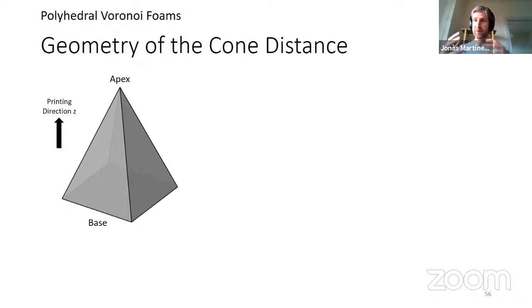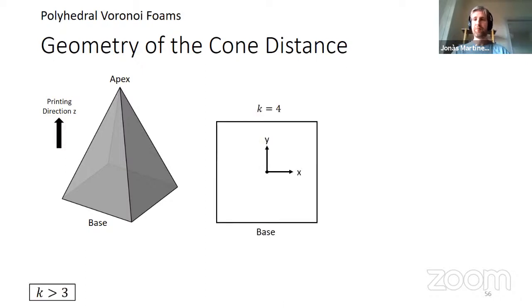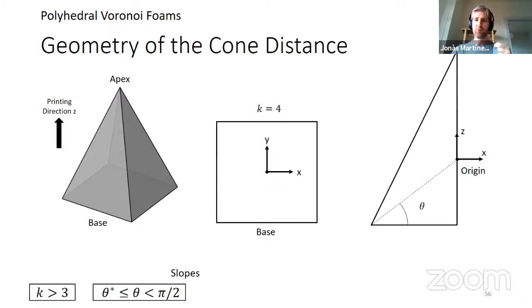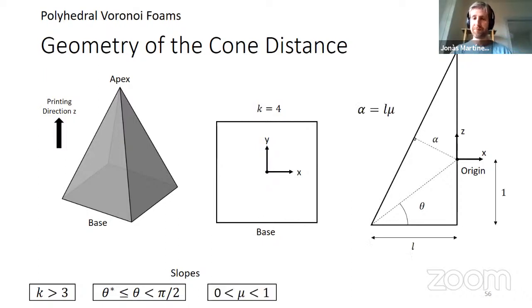So we did a parameterization of this family of distances. How do we do it? Basically, we consider a pyramid going in the printing direction with a base and an apex. The base is parameterized by a regular polygon with K faces. And then we have different parameters that control the origin and that control the ratio of the lateral side and the distance to the apex. So basically the aspect ratio. So you see, these are the parameters that appear below.